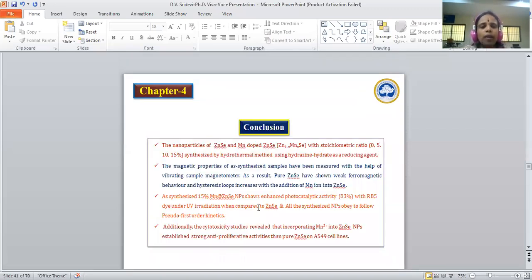Conclusion: the nanoparticles of zinc selenide and manganese doped zinc selenide nanoparticles with a stoichiometric ratio of 5, 10, and 15% have been synthesized by hydrothermal method using hydrazine monohydrate as a reducing agent. The magnetic properties of the as synthesized nanoparticles have been measured with the help of VSM. As a result, pure zinc selenide has shown weak ferromagnetic behavior, and the hysteresis loop curves increase with the addition of manganese ion incorporation into the zinc selenide nanoparticles.